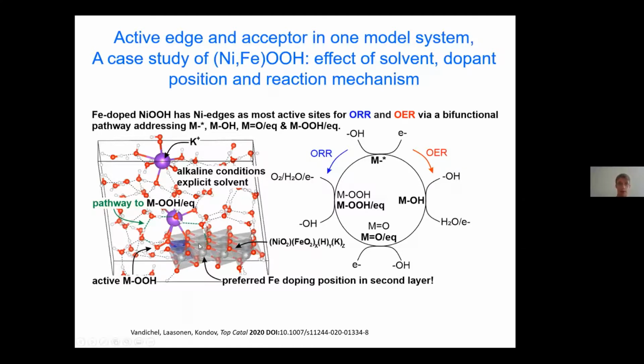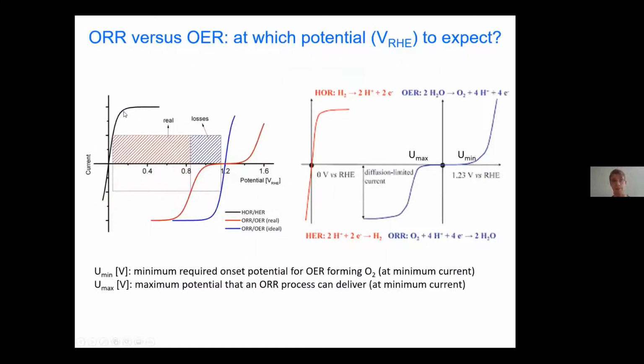And then we can study on this nickel oxyhydroxide, what is actually the preferred iron position? Where is the preferred iron doping? We can do this study for both ORR and OER. So ORR, to see the distinction, for the ORR process, we work at a potential that is lower than 1.23 volt.